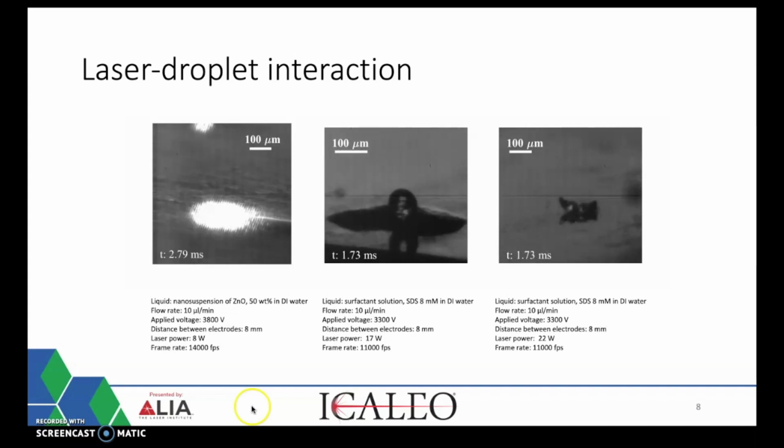The upward bouncing of the droplet is due to localized rapid evaporation of the liquid at this point, and this results because of the Leidenfrost effect. Here we see that rapid evaporation causes accumulation of vapor underneath the deformed droplet and builds up pressure that ultimately propels the droplet upward, as we can see in the animation on the right.